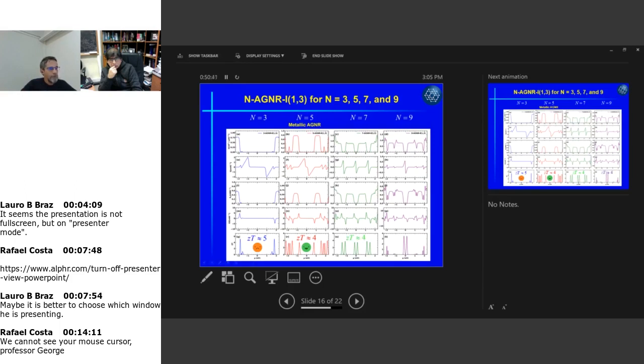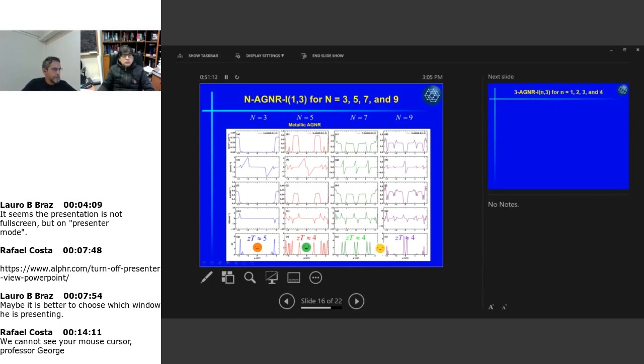And the other two here, it more or less kept the same value it had after we transformed it. Remember that we had two values there, 5 and 4. 5 was for capital N equal 3, and 4 were the values for N equal 7 and N equal 9. So here we maintain the same ZT value. The heterostructure didn't have a big influence. So we are so-so with this result.